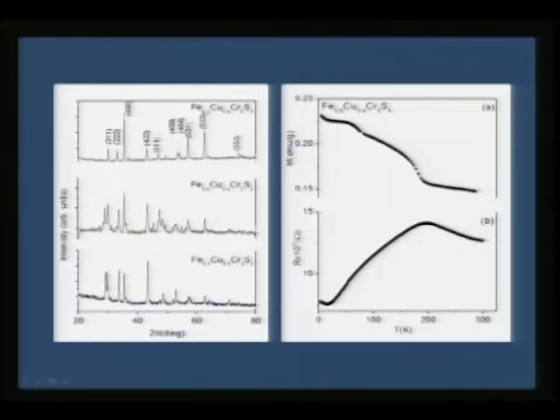So, you can see you can play around with a variety of compositions of iron copper in this spinel, and what we have found here is that for an optimum concentration of 0.6, 0.4, you can get the Tc to be around 200, and that also shows a typical metal to insulator transition going with the Tc. Therefore, one can easily prepare such oxides.